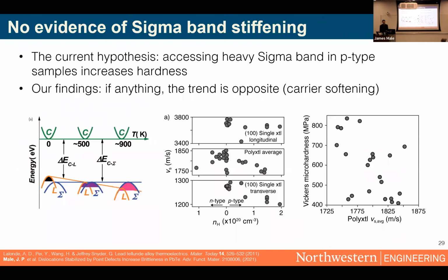The first thing we found was in those speed of sound measurements. There are a few studies that have hypothesized lead telluride is brittle when it's P-type because of the band structure. Of course, as I mentioned earlier, the valence bands of lead telluride have this unique band convergence effect, but the conduction bands do not. So I guess the idea was somehow that band convergence was altering stiffness and hardness.